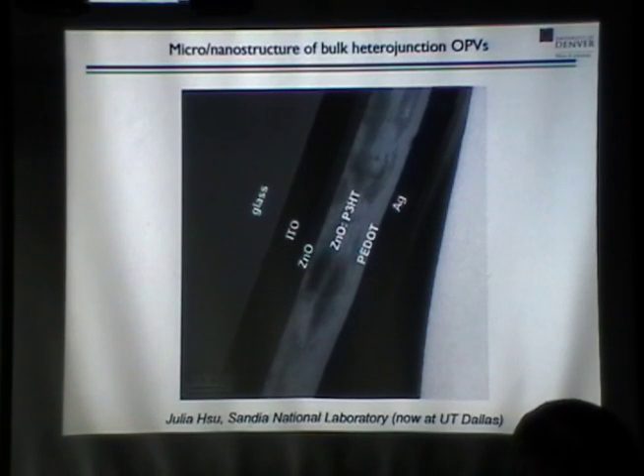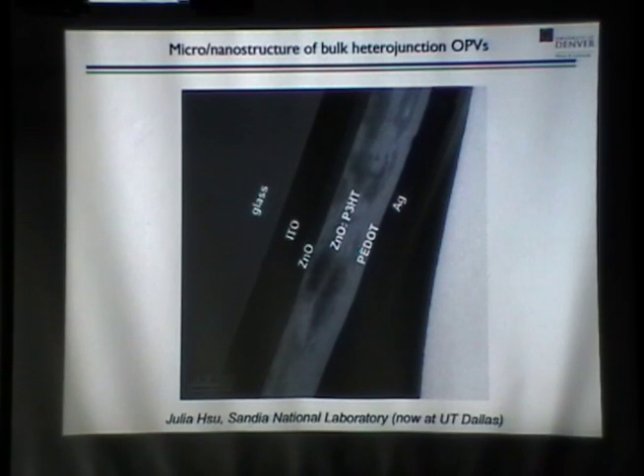So just to give you an idea of what these things really look like, we can do cross-sectional transmission electron microscopy. These were done at Sandia National Lab by Julia Hsu, who's now at UT Dallas. So in this case, we physically break the device and we encapsulate it in an epoxy so that we can do an edge-on TEM, and you get an idea. Here's the glass substrate, here's the indium tin oxide, here's the zinc oxide. This is an inverted device.